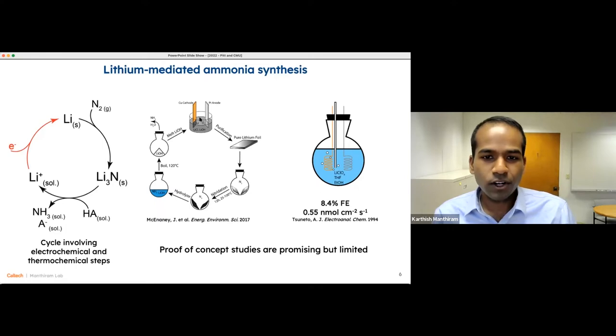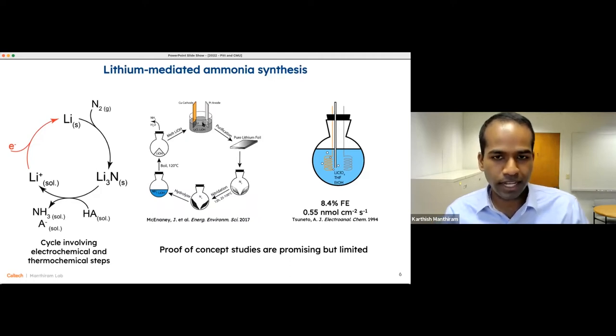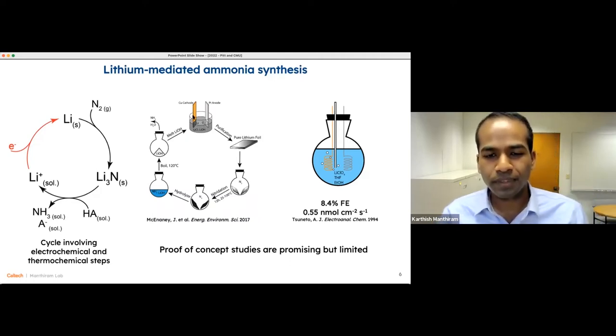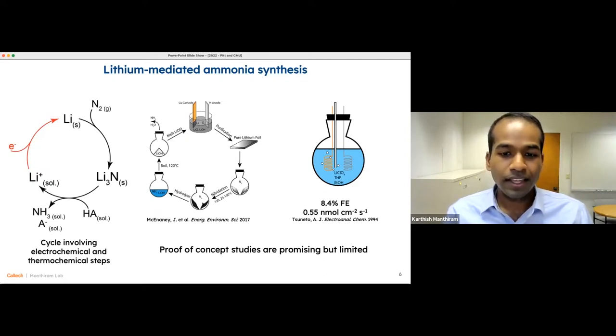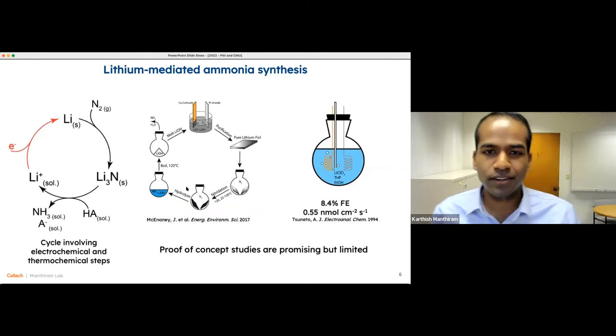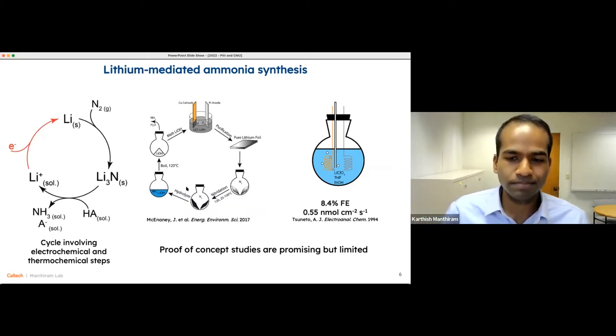So one can, for instance, start with a lithium chloride, lithium hydroxide bath. This is a molten mixture at 400 to 500 degrees centigrade. Plate out lithium metal, scrape that off, put it into a beaker, introduce dinitrogen, then hydrolyze that such that one produces ammonia, boil off the ammonia in water, leaving behind lithium hydroxide, and then melt that lithium hydroxide again. So this is a batch-wise process by which one can see that this chemistry does in fact work. One can get an 8.4% Faradaic efficiency for making ammonia.